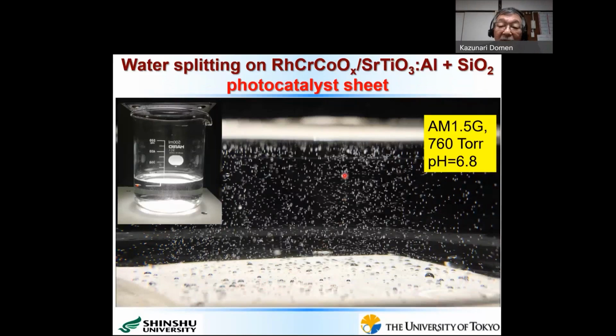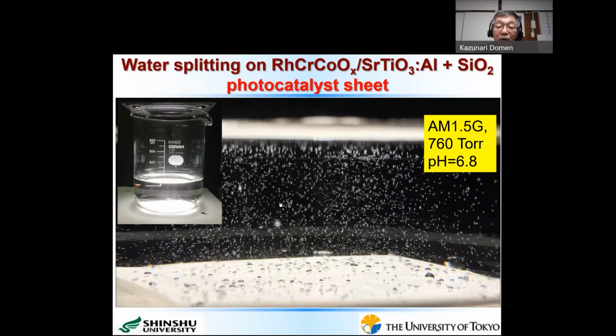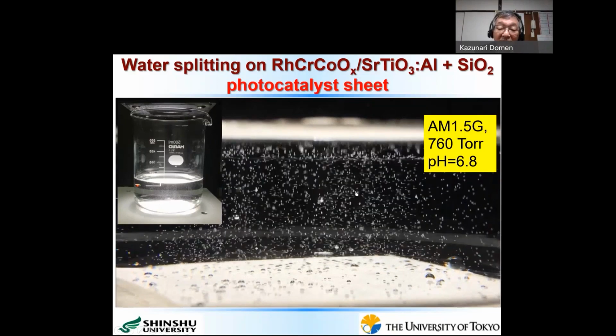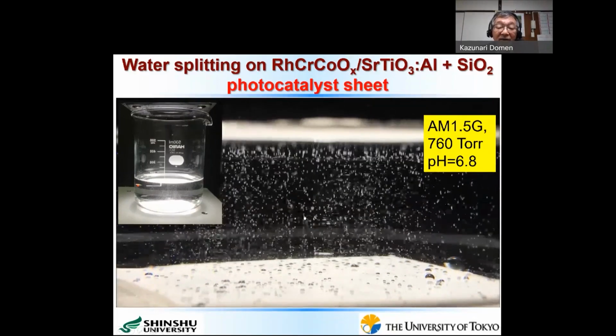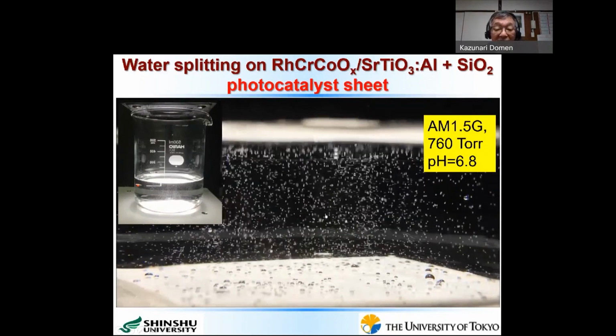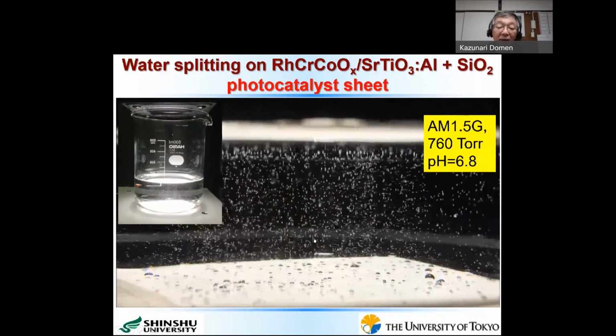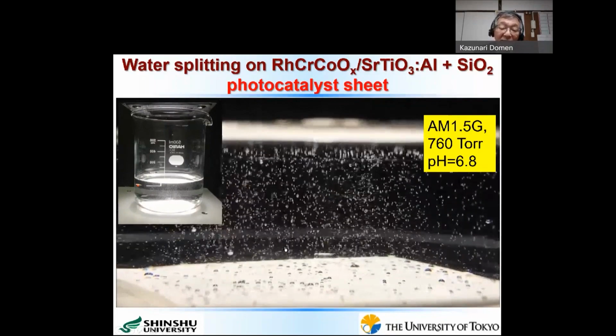And then we prepare the so-called photocatalyst sheet using these photocatalytic materials and nano-sized silica materials on a glass plate, just spray coating, then drying up at about 80 degrees C in air. Here we have a 500 milliliter beaker just filled with distilled water. Then if we put this beaker outside under sunlight or just irradiate by a solar simulator, we can get this kind of bubbles coming out. These are bubbles of hydrogen and oxygen exactly in 2:1 ratio, which is decomposed by using ultraviolet UV light